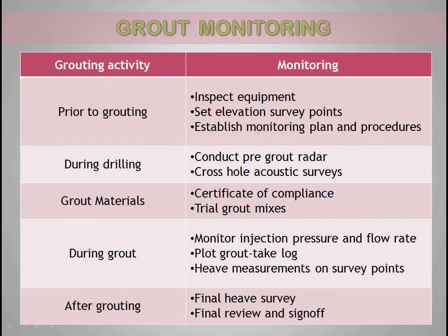You have to be very careful and monitor the injection pressure and the flow rate, which is very important, because too much pressure may cause some heaving above the ground. Excess quantity may also lead to unexpected cracks below the soil. So you have to carefully observe the pressure with the help of the pressure gauge available on the grout pump, and the flow rate, the quantity. You have to control the quantity of grout material entering the borehole.